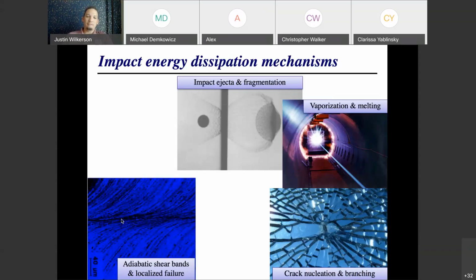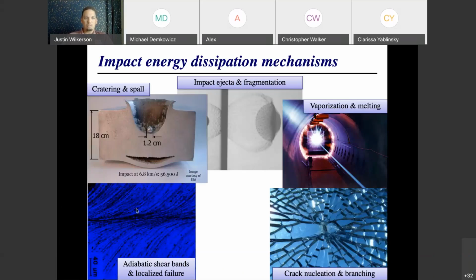a runaway effect. It tends to happen at high rates because at high rates, thermal conduction is pretty slow. It's not necessarily totally negligible, so this word adiabatic is not quite right. It should probably be quasi-adiabatic shear bands, but that's the terminology that we've had for a while. And so if you load the material slowly, then there's time for thermal conduction to take that heat away, and you don't have the instability forming, at least not as severely. Again, I'm not going to talk too much about that failure mode today. What I'm going to talk mostly about here is actually spall failure.